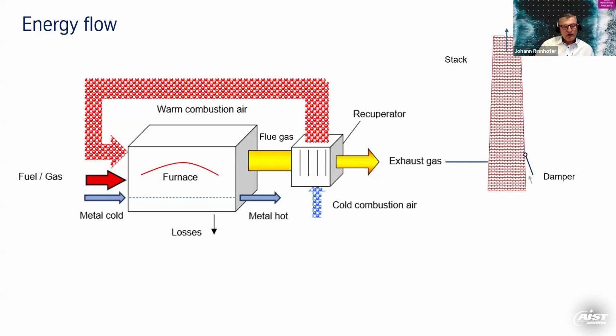So 1 kilogram of air has approximately 1 kilojoule per kilogram and Kelvin. Steel has 0.6 approximately at 1000 degrees. So 1 kilo of air has a higher heat capacity than steel.